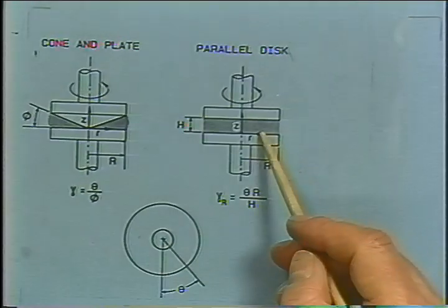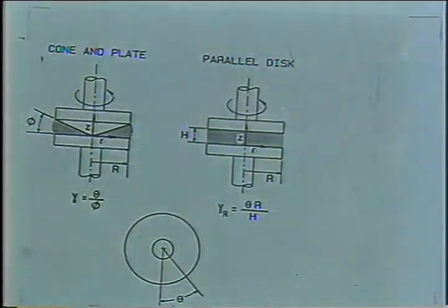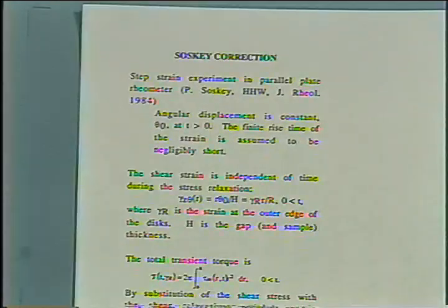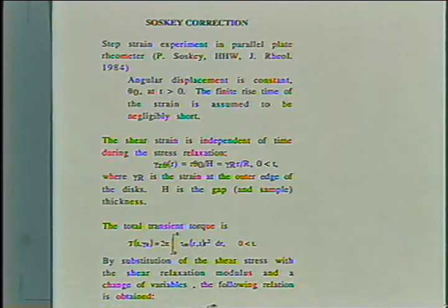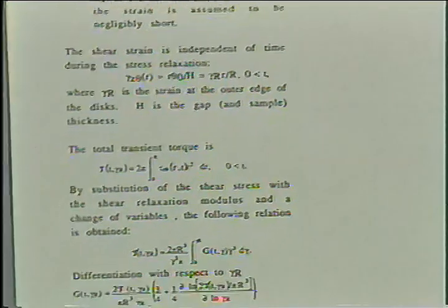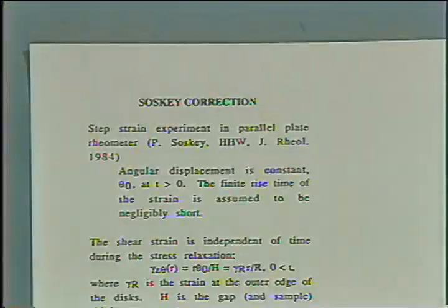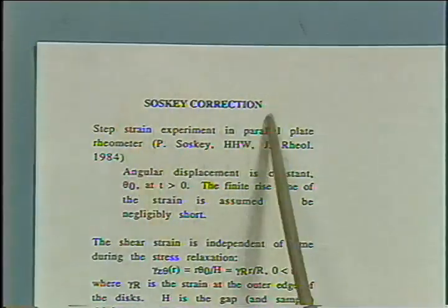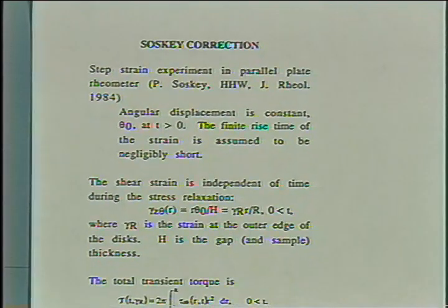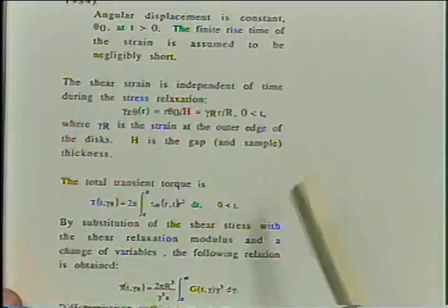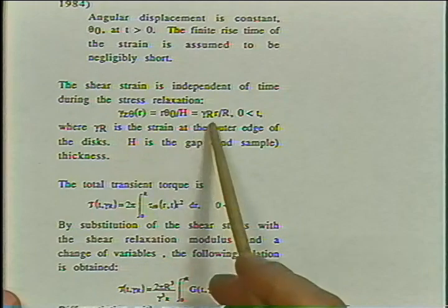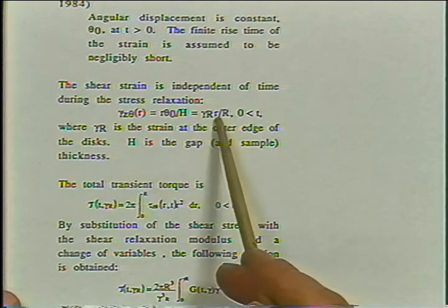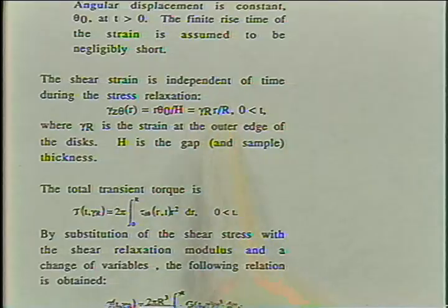Also, if you work with suspensions and want to measure the stress-strain response, you would like to do this in a plate-and-plate geometry. And for that purpose, Soskey thought he should do the following. He should use the plate-and-plate geometry, and I want to discuss Soskey's correction, which is really equivalent to the Rabinowitsch correction, but this is now for step strain. He imposes a step strain on the sample, and this is the value of the strain at the outer edge multiplied with small r over R, so this is the linear increase of the strain for our inhomogeneous experiment.